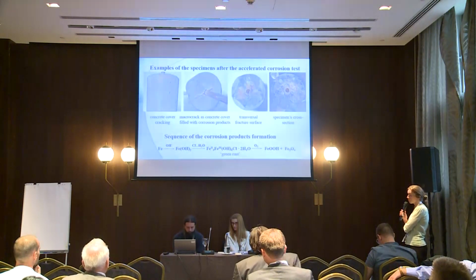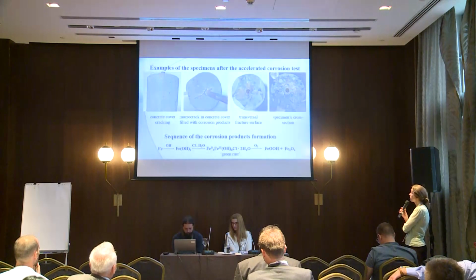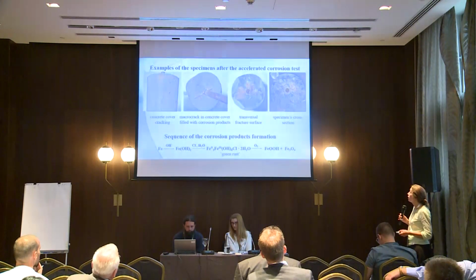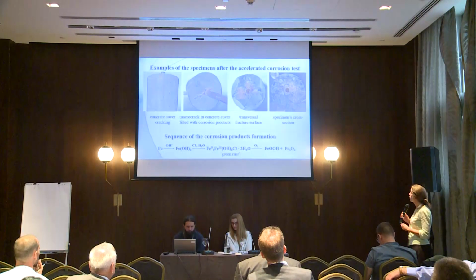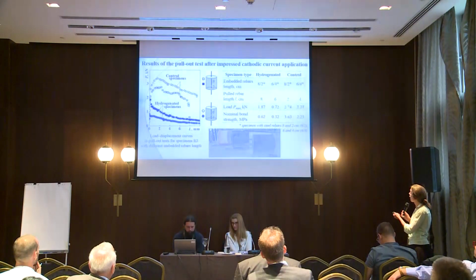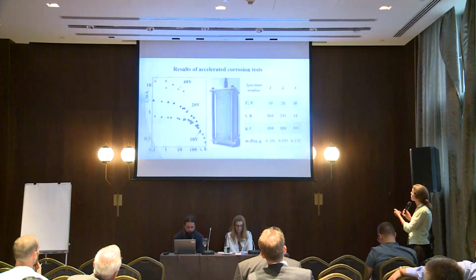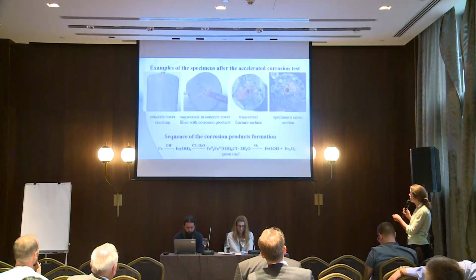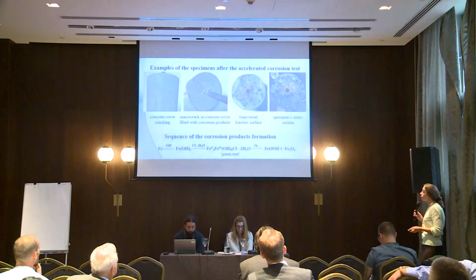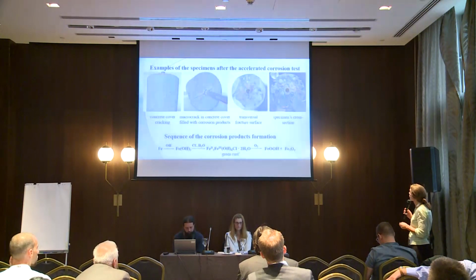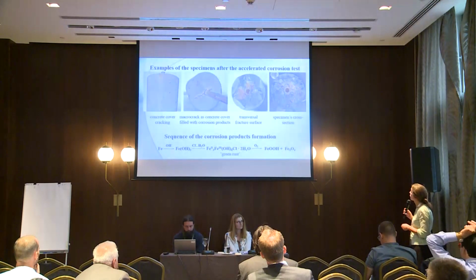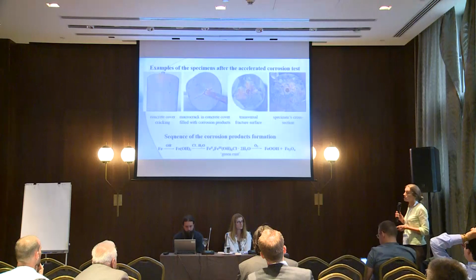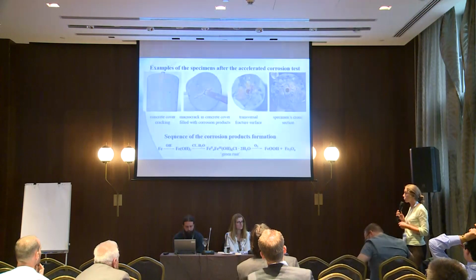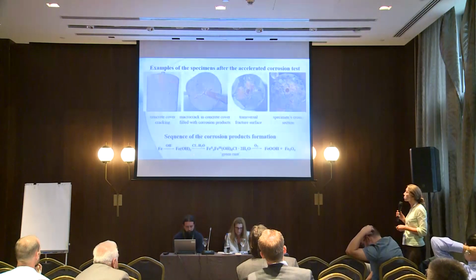Usually the depth of corrosion product penetration into concrete is only several millimeters. It was shown by many researchers. But in the present study, deep penetration of corrosion product is revealed. Corrosion products seem to be distributed not only in the near-surface layer in concrete defects, but also in the unbroken concrete matrix. It could be explained by the formation of soluble species in the course of corrosion.